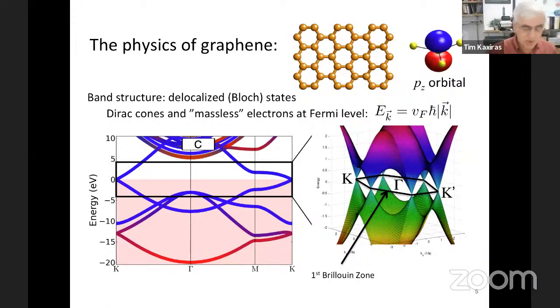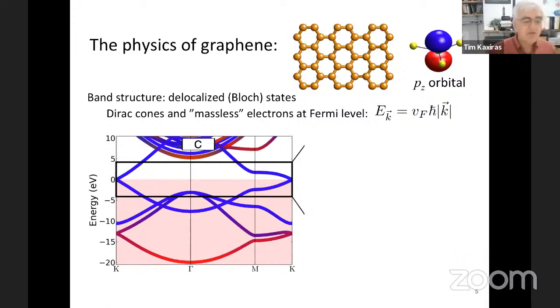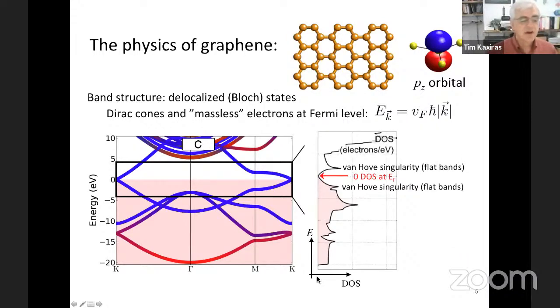But what's more interesting is that the linear dispersion relationship is valid only for a narrow range of energies near the Fermi level, near the charge neutrality point, as it's called for a neutral system before being doped. And in fact, if you look at the density of states, the horizontal axis now is density of states and the vertical is energy. So here is the Fermi level for the neutral system, the charge neutrality point. And this is the density of states produced by the linear dispersion relationship. But if you go away from it, you see that the density of states rises sharply.